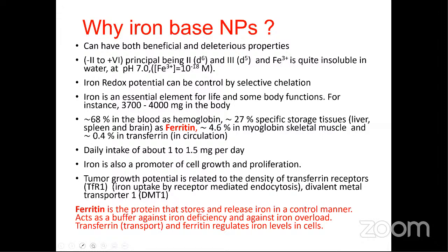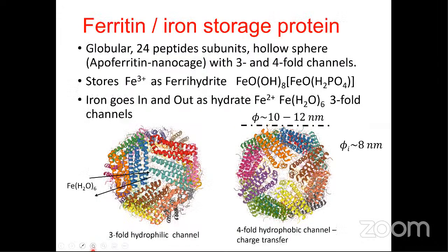Then what happens with ferritin? This is a very nice nanocage. We have drawn it here. It's a globular nanocage, 24 peptide subunits, and has inside apoferritin, which is the ferritin without the iron 3, which is stored as ferrihydrite. You can see that there are some threefold channels where 3 of these peptide units meet. There's a hole here, and through this hole, hydrated iron can go in and out.